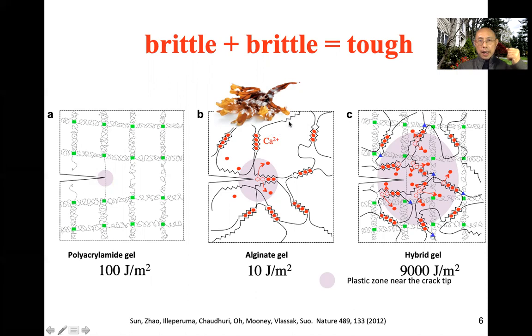This alginate came from algae. It's a biopolymer. This polymer has a negative charge on the chain. And in the water, it's a hydrogel. In the water, you have calcium ions, and these calcium ions bridge the negative charges. So this is an ionic crosslink. When a crack comes along, it needs to break this ionic bond and this ionic bond, but doesn't really break ionic bonds in the bulk. As a result, the toughness is low. It's on the order of tofu and jello, 10 joule per meter squared.